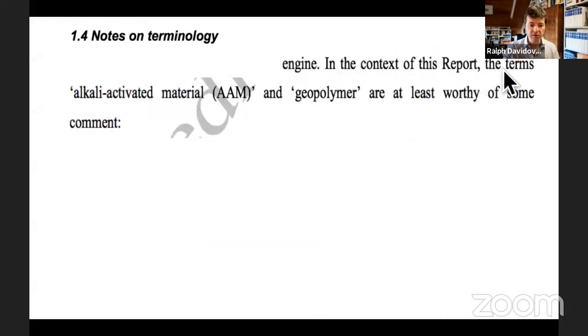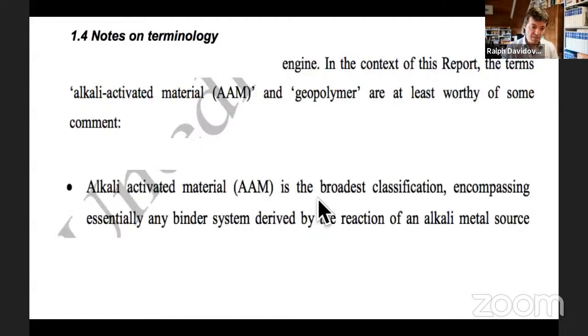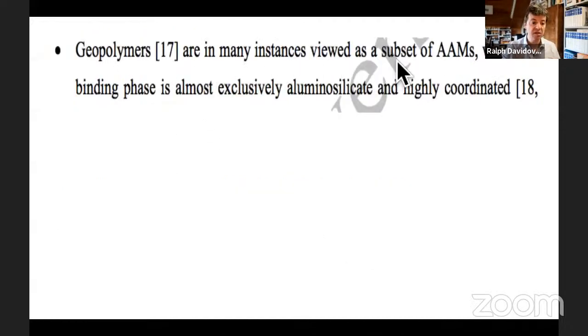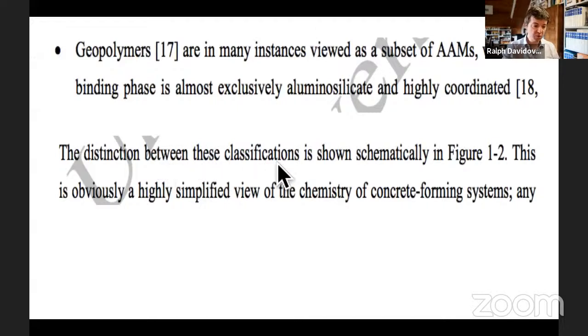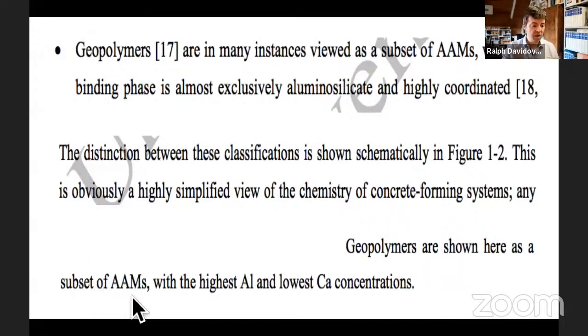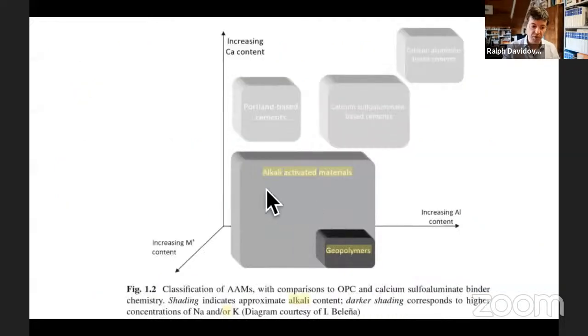Notes on terminology. In the context of this report, the terms alkali activated materials and geopolymer are at least worthy of some comment. AAM is the broadest classification encompassing essentially any binder system derived by the reaction of an alkali metal source. Geopolymers are in many instances viewed as a subset of AAMs where the binding phase is almost exclusively aluminosilicate and highly coordinated. The distinction between the classification is shown schematically in figure 1-2. This is obviously a highly simplified view of the chemistry of concrete forming systems. Geopolymers are shown here as a subset of AAM with the highest aluminum and lowest calcium concentration.